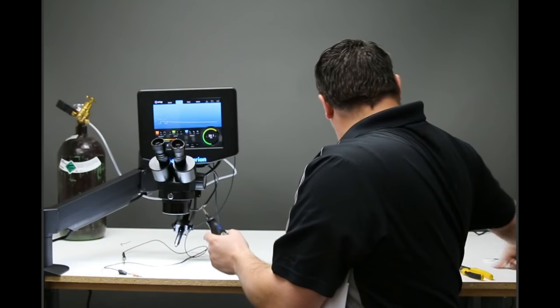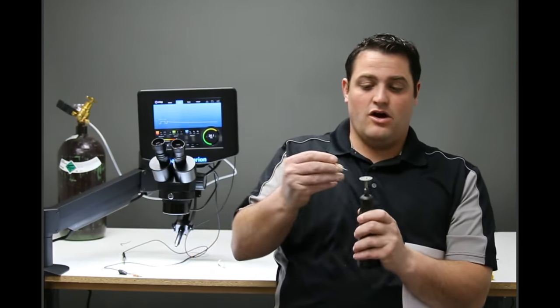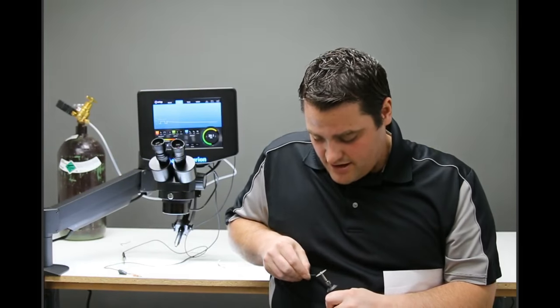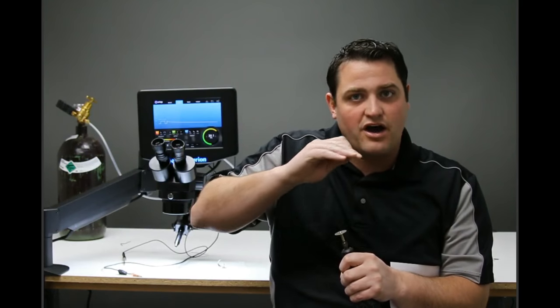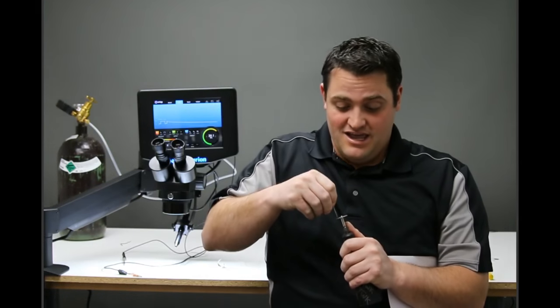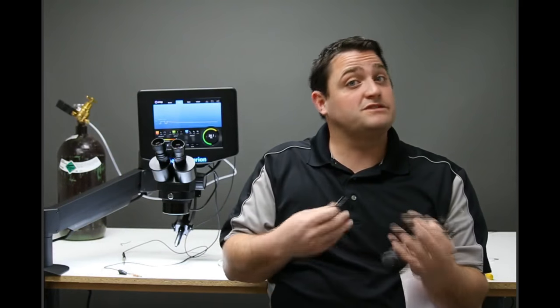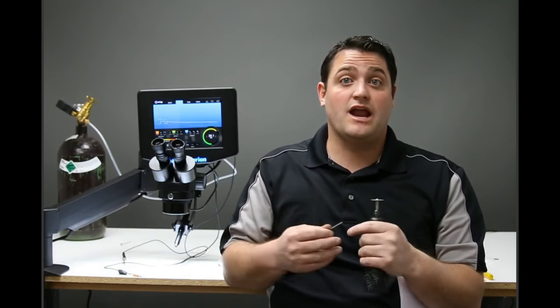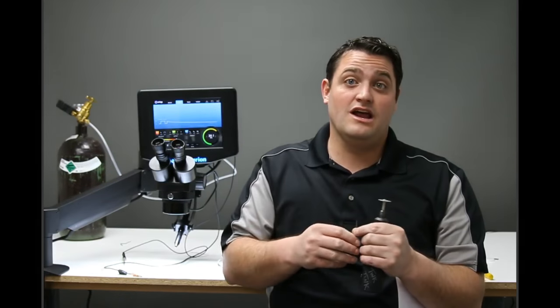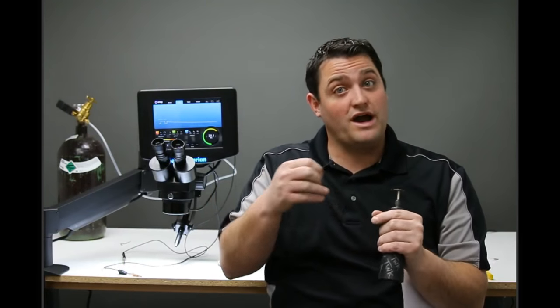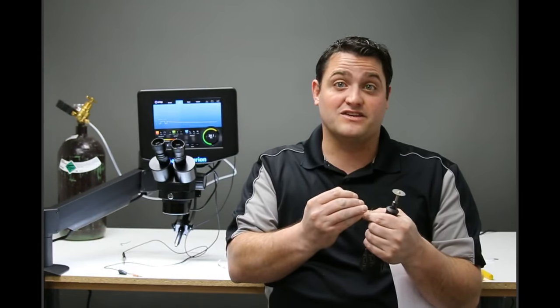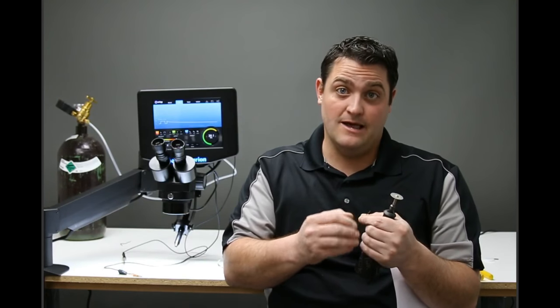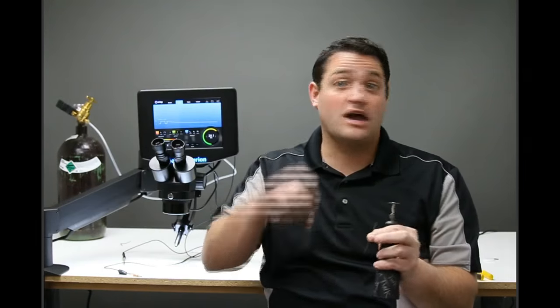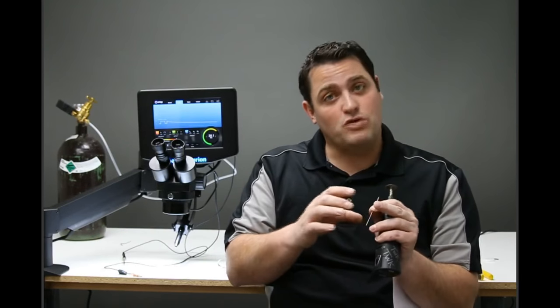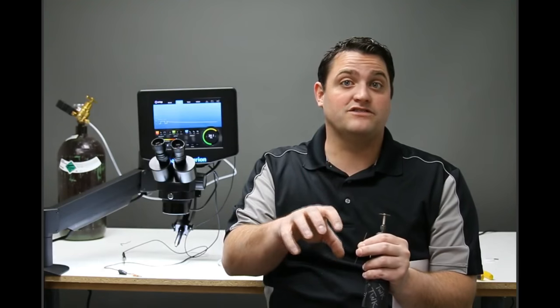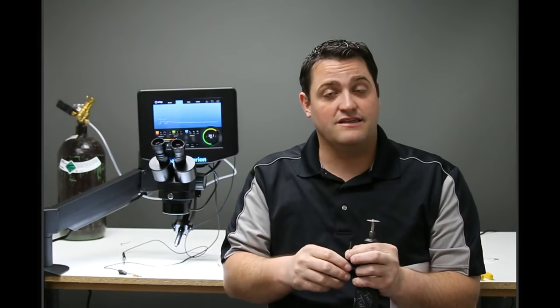So I've got here an electrode. I'm going to sharpen it as normal, like here. Then I'm going to take it and truncate it, or cut off that tip of that electrode just a little bit, depending on how much energy I want. Specifically with silver, if I need a lot of energy and I want to make a big weld, I've got a big, thick piece of silver, then I'm going to be truncating this out quite a bit, maybe up to about 80% of the total length of where your sharpening point is. What that's going to do is spread that energy. It's not going to punch as hard right on the surface of the metal, but it's going to spread that out and allow it to heat a wider area, but still give you the weld and the melt size that you need.